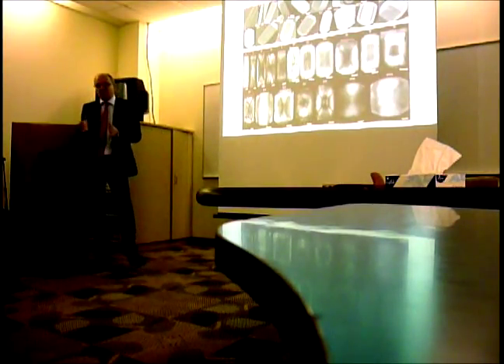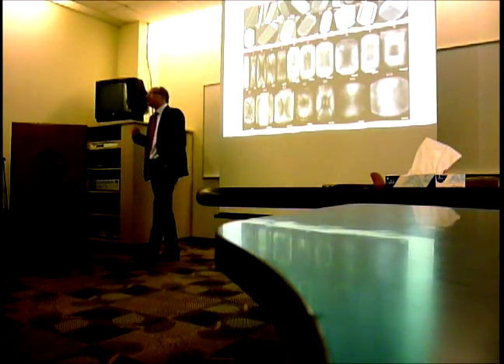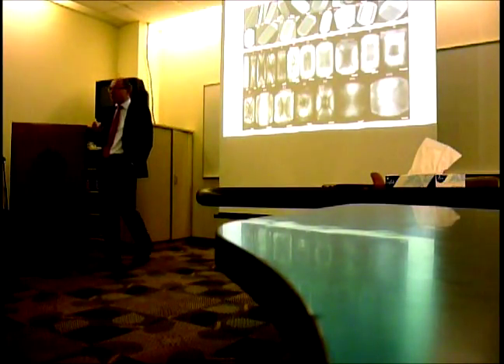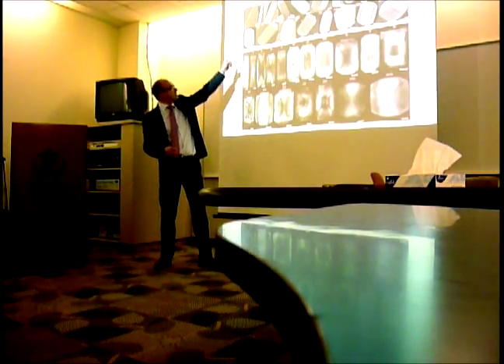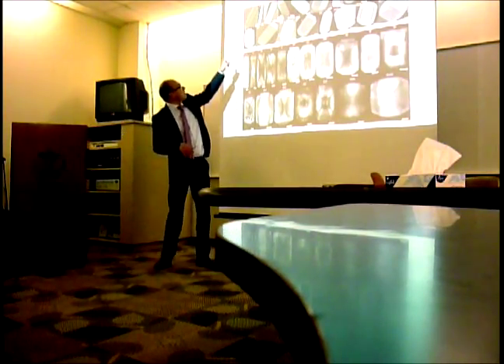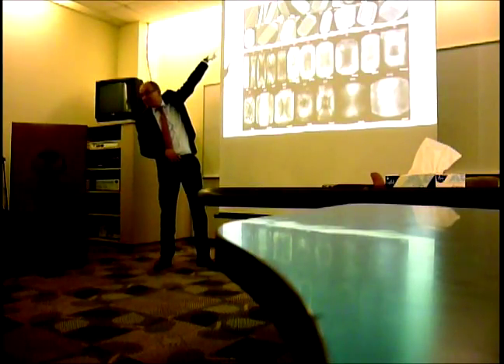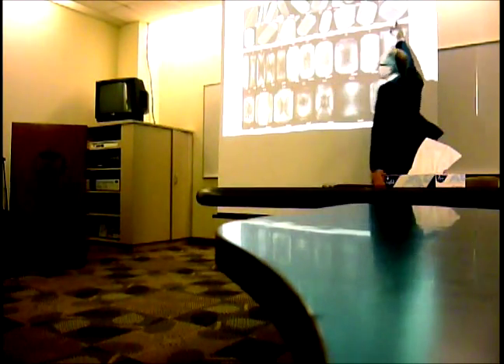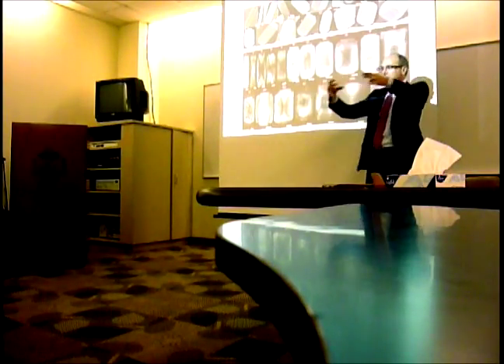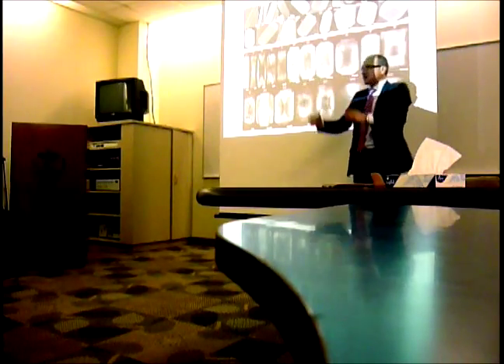But for this we did a very extensive study, because now I'm going back to a very long discussion in the zeolite history, since the first synthesis of ZSM-5 as an important catalyst material in the 70s. Almost everyone had been disputing the intergrowth structure of zeolite ZSM-5. So we thought, let's now take a whole range of crystals, as you can see here, from different places on Earth, made in different labs. From the one which I already discussed, you've seen it before, it's a very nice cube. You can have them very elongated, or you can make them almost like a cube. And then you have different forms. So we analyzed them in great detail.